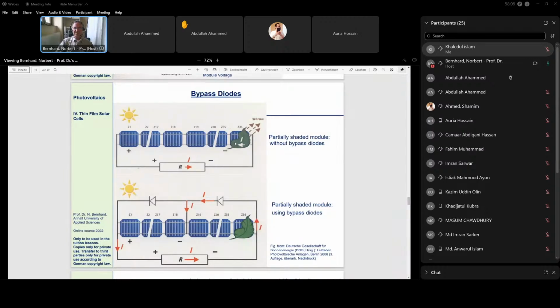and then if one cell is fully or partially shaded, in this case partially shaded, roughly 3/4 of the cell are shaded, 1/4 is unshaded, then we have a problem, because all these cells are in series, and I said already the weakest cell determines the current. And in this case, you see the current would be only roughly 1/4 of the current if all cells would be unshaded. And that means this one shaded cell makes all the unaffected cells reduce the efficiency. That means we would lose 3/4 of the efficiency of the whole module.